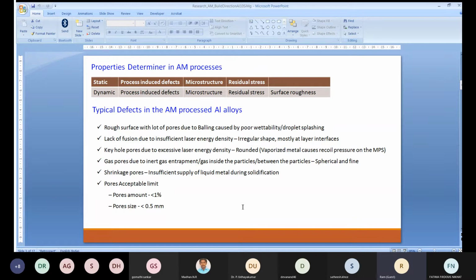Another very important parameter in printing is laser energy density. It is laser power divided by scanning speed times layer thickness times hatch distance. It should be optimum, not too low and not too high. If it is too low, you have a problem called lack of fusion porosity, which is usually found at layer interfaces, and the shape is irregular.